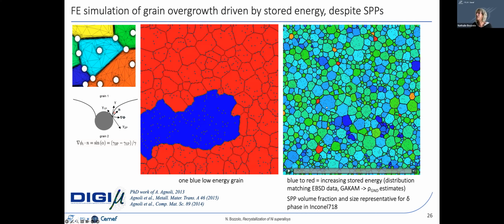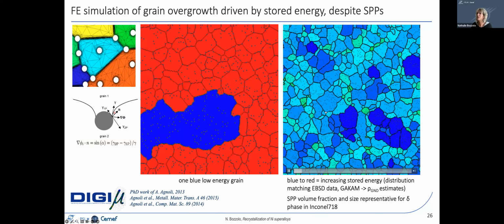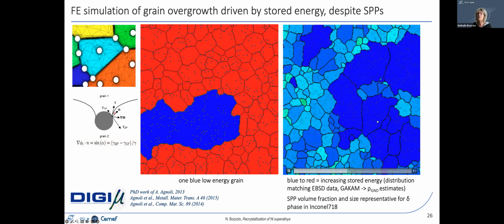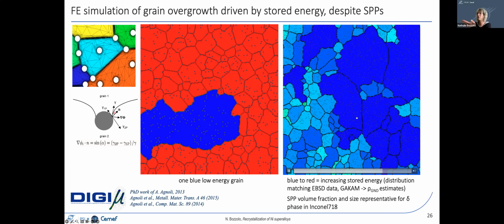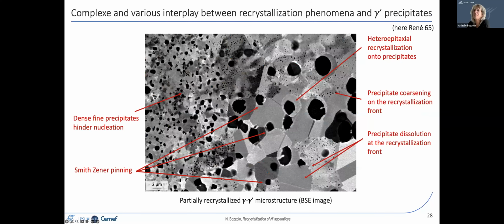So you see again that for grains with similar stored energy levels, the interface does not move, while the grains which had initially low stored energy levels can grow and invade the microstructure, ending up with a very heterogeneous grain size distribution. All right. So in nickel-based superalloys, we have seen recrystallization phenomena.